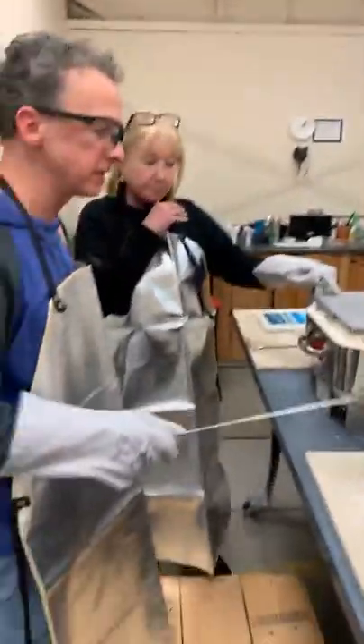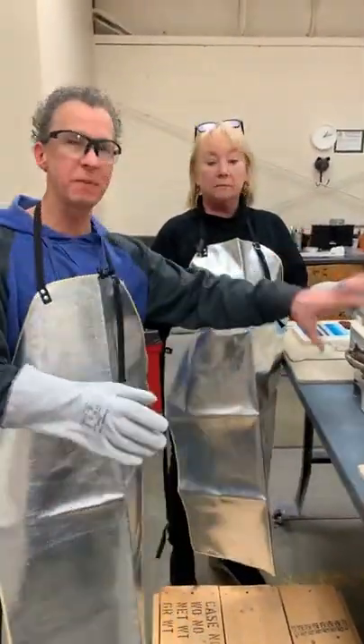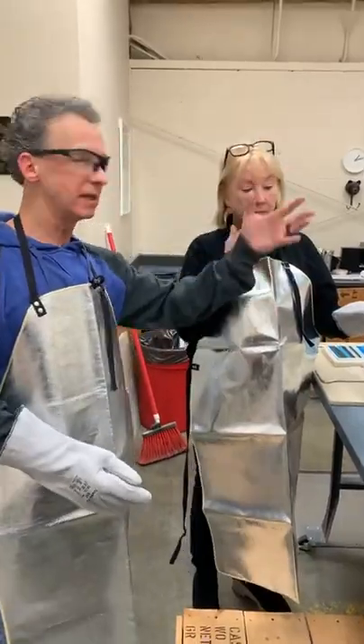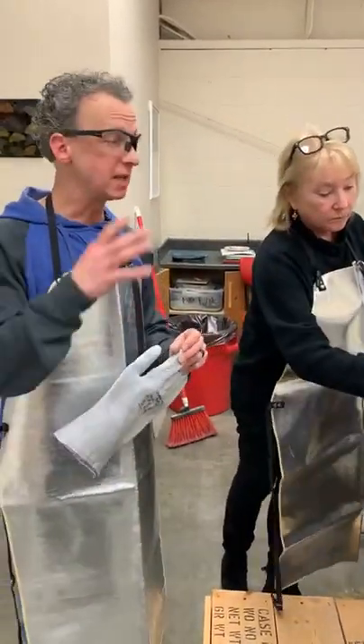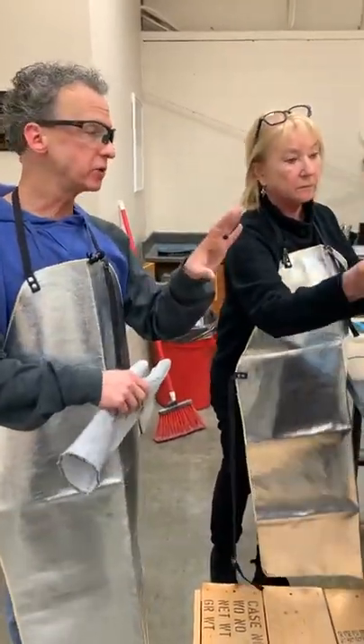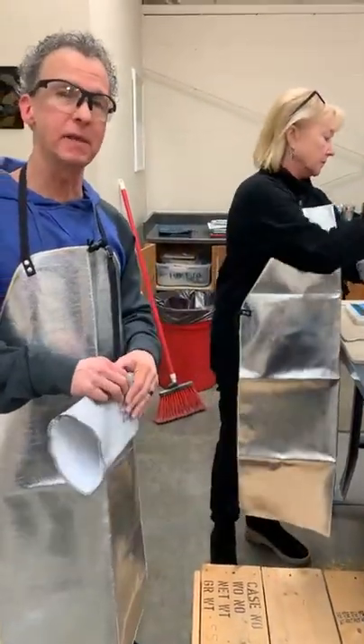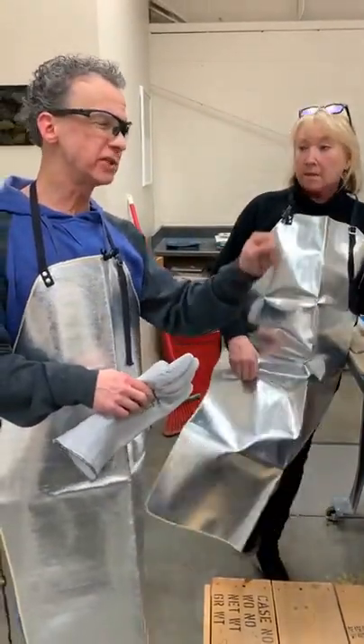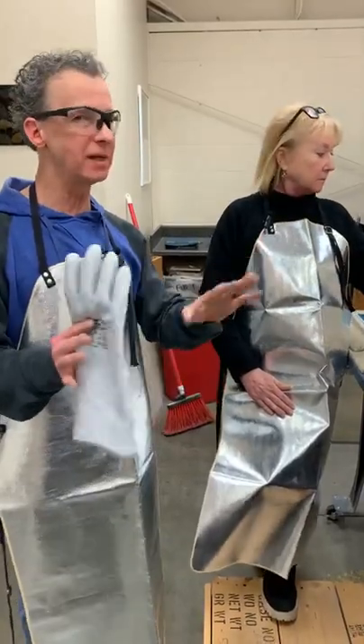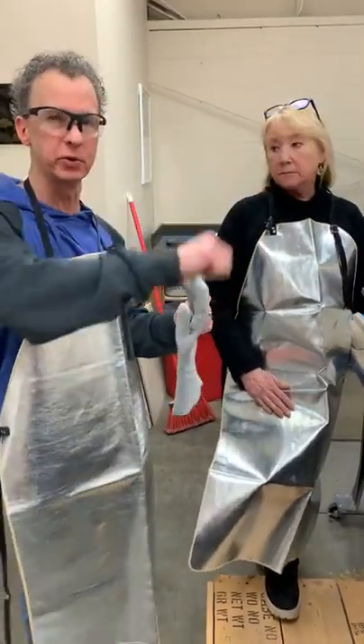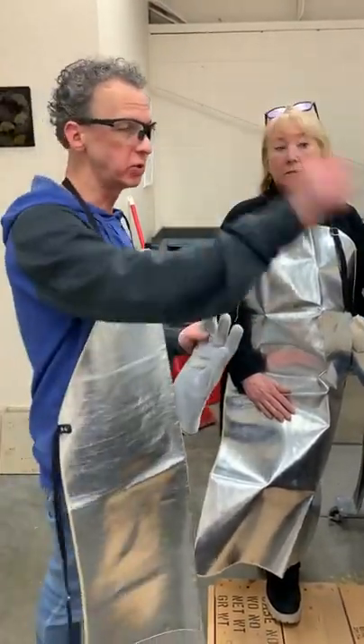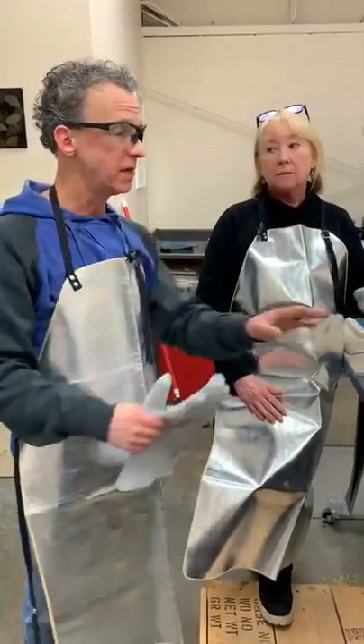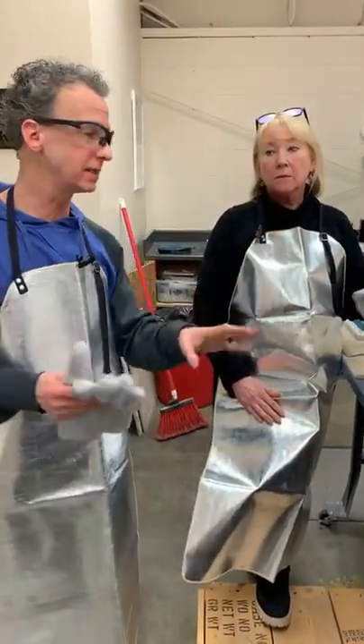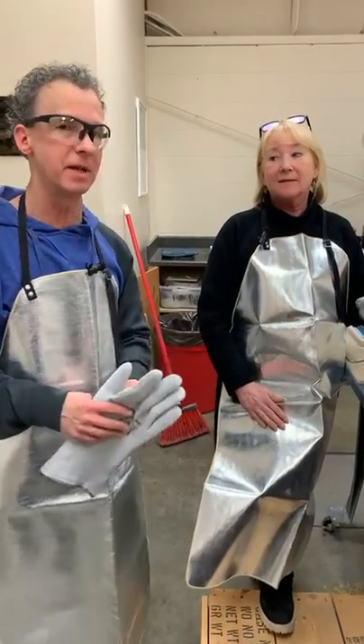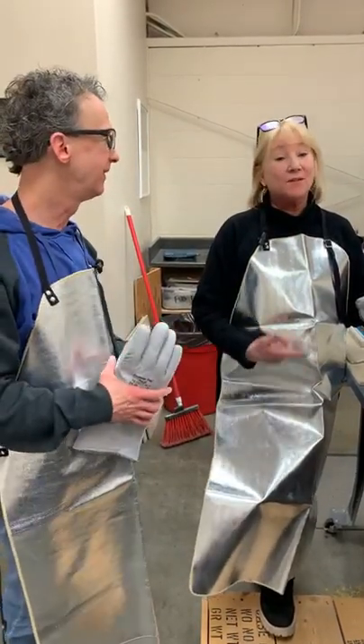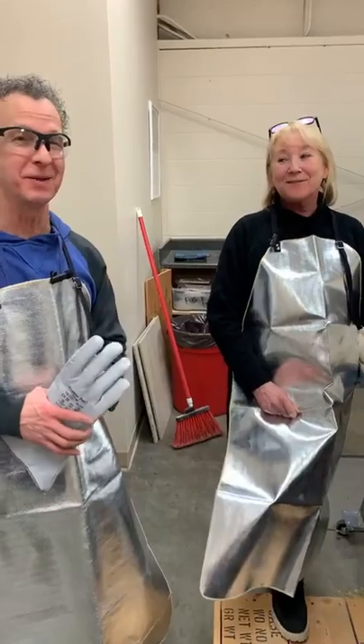So what happens is, we shut the power off, and then as we open the lid, obviously we lose a bunch of heat from that, and it cools down quickly. Ours was really quite hot. We've mentioned a couple times, if this was 1,700 degrees, you might get 2 rakes, like 2 pulls through it, and that would be it. Then you would cool off the tool, close the lid, turn it back on, and let it heat back up. At this rate, it probably would take about 10 minutes to do that. But that was sweet, we got the glass so pretty hot.